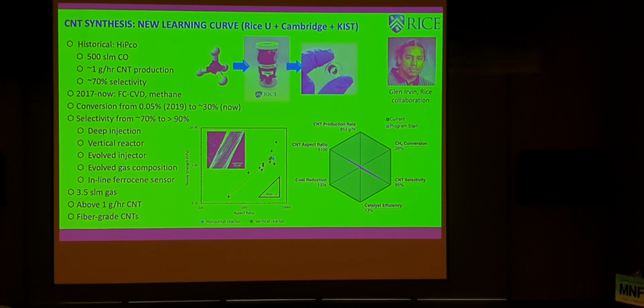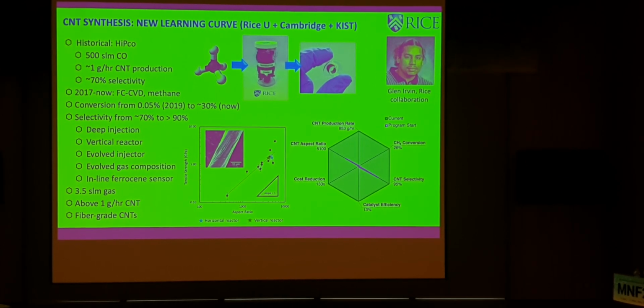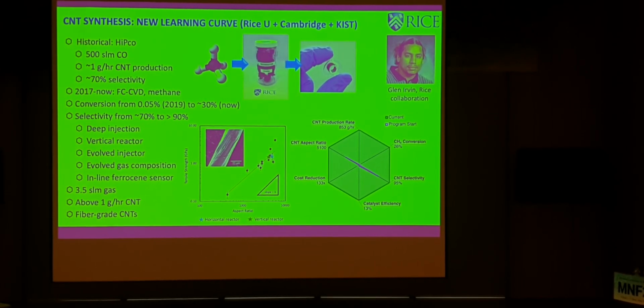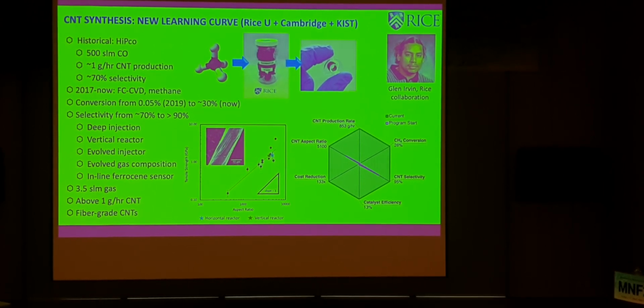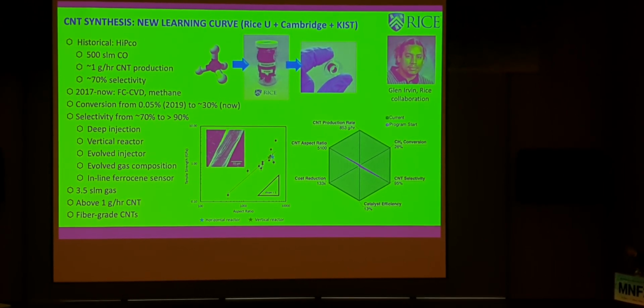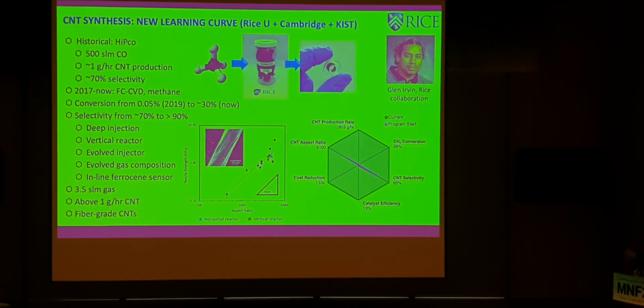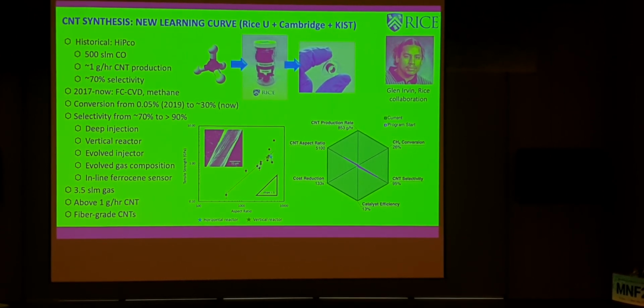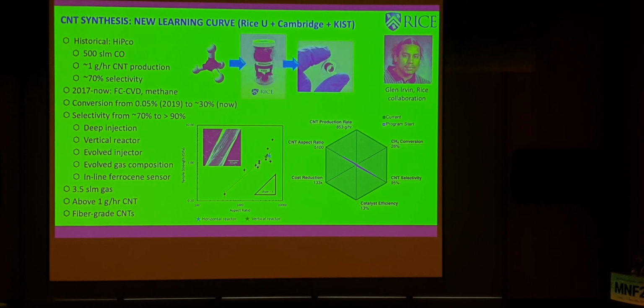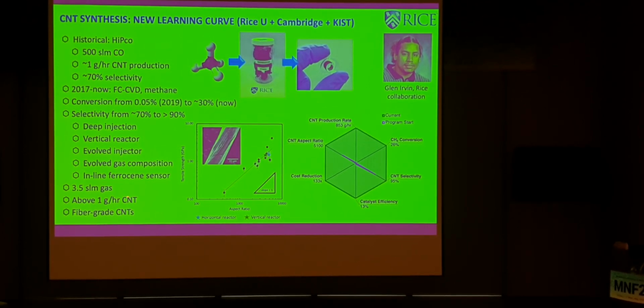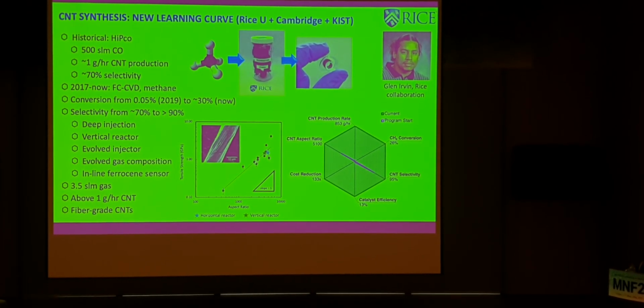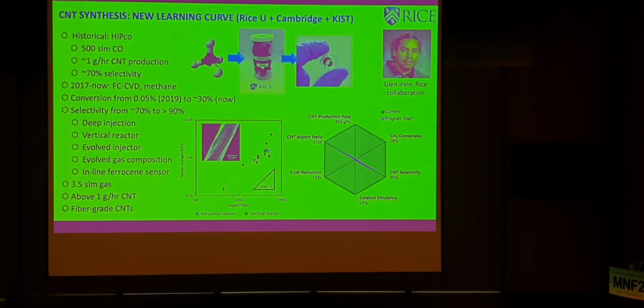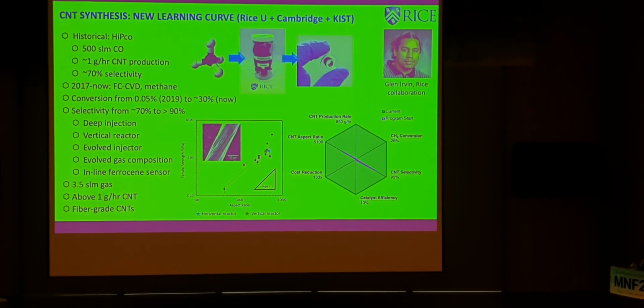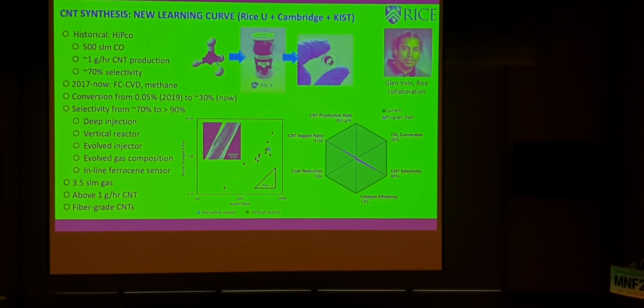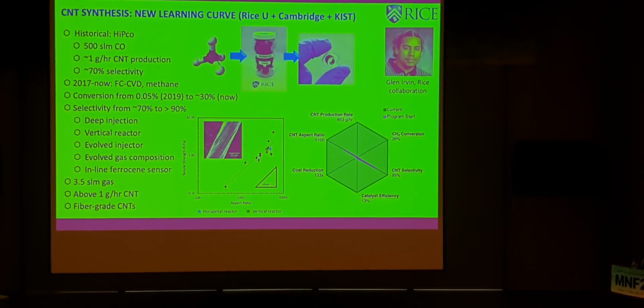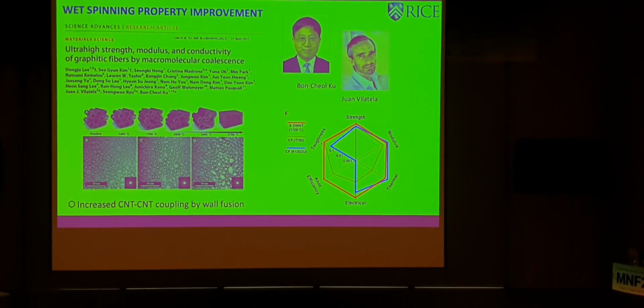These new reactors with a deeper injection are running about 3 to 4 standard liters per minute of gas, and they're making over a gram an hour, and the material is much better. That's roughly a measure of the intensification, because most of the energy goes into heating up those gases, right? And this is just a scratch. These reactors are still mostly running inert gas, right? So if we can do what David Gaines and his team have done, maybe we'll do it with them and get that inert gas lower, it's going to be very important. But on spinning, there's been big improvements.